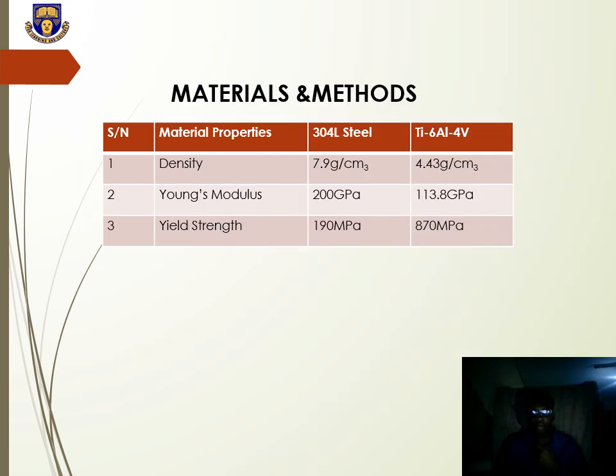Then the material properties of the two materials are in consideration. We took material properties of density, Young modulus, and the yield strength. So the density of 304L steel was 7.9 gram per cm cube. That of the titanium alloy was 4.43 gram per cm cube. The Young modulus was 200 gigapascals for steel, and the Young modulus for the titanium alloy was 113.8 gigapascals. The yield strength for steel was 190 megapascals, and the yield strength of the titanium alloy was 870 megapascals.